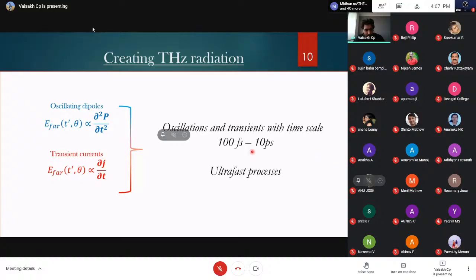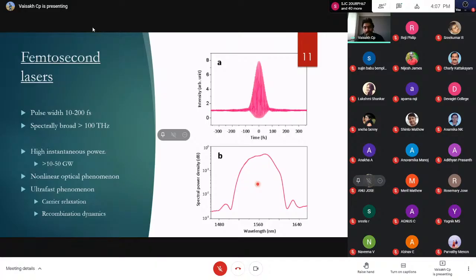So what one would need is to have oscillations and transients that take place in a time scale of hundreds of femtoseconds to 10 picoseconds, ultra fast processes. So the question is, how do we generate such very short transients? Enter femtosecond lasers. These lasers emit pulses with a width of tens to hundreds of femtoseconds. They have a very broad spectrum. In the figure, you can see the intensity profile and its Fourier transform, the spectral component in Fourier space.